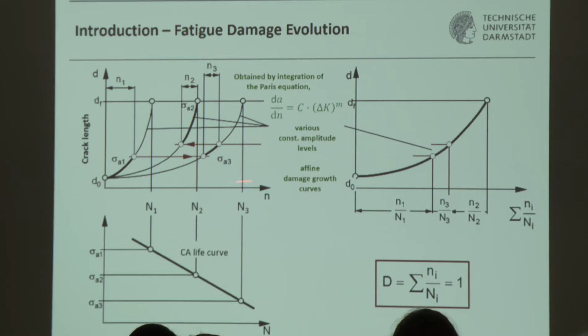And this experiment now is the application of N1 cycles with a large amplitude. And in this graph, this means that you apply a ratio of lowercase n over uppercase N, and you end up at the very same crack length. Then you continue with cycles of sigma A3 amplitude, and then with the rest of it, and you see in this graph that you only have the chance to start at 0 in the normalized life usage ratios and to end up at 1, and this is simply the Palmgren-Miner damage accumulation rule. So simple application of fracture mechanics will not solve the problem, because the results are totally identical to a Miner damage sum calculation.